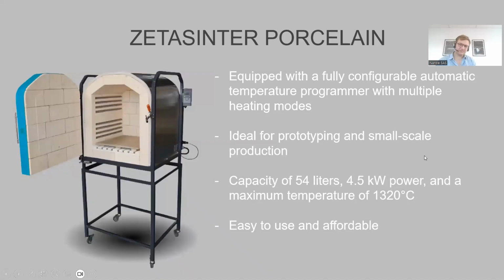So the second thing we're launching with this filament is a furnace, and we're really very happy to be able to offer this furnace, again, with our partner, which is Serinov. This furnace is made in Europe. It's made by this partner, and that's one of the other interests of porcelain. The furnaces that you need to sinter porcelain at 1250 degrees Celsius are much more simple than a furnace for high temperature ceramics, which allows us to have a bigger furnace at a lower cost. And of course, that's very convenient.